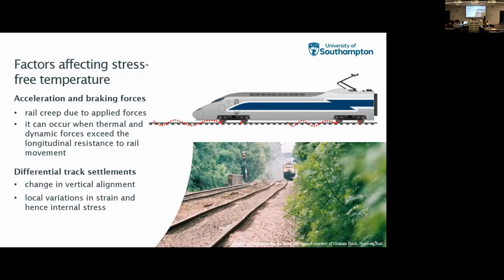The fourth factor is differential track settlements. As you can see in this picture, differential track settlements change the vertical profile of the rail, and thus there is a local variation in strain, and hence this factor does not require any other conditions such as poor fastenings or ballast. So it can affect the stress-free temperature permanently.